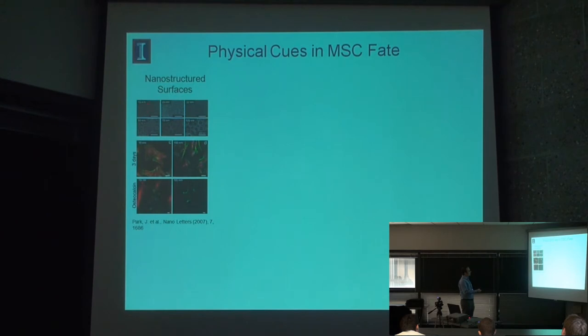But essentially, when they put mesenchymal stem cells on these surfaces, they found that cells adherent to these small nanotubes were able to spread out, get a high degree of cytoskeletal tension, and a robust focal adhesion formation throughout the cell, compared to cells that are adherent on these large nanotubes, where they remain rather spindly, and they don't adopt a stable cytoskeletal configuration. And then after several weeks, when they went in and stained for markers associated with bone cell differentiation, they found that cells that were spread out, had this healthy, well-developed cytoskeleton, expressed higher levels of differentiation markers for bone.